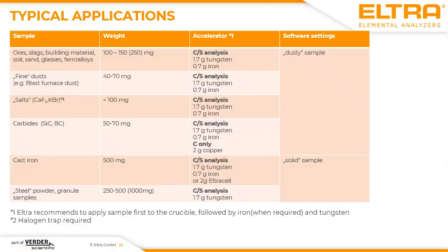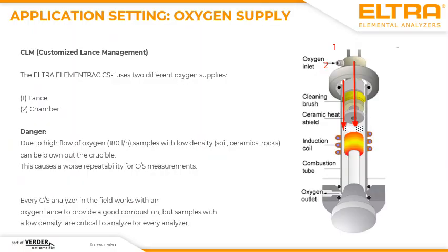On the right side of this table, you'll find the information software settings, dusty and solid sample. This is especially created for the settings of the Elementrac CS-i because this analyzer can provide you different combustion steps to make sure that your sample is on the one hand combusted completely, but on the other hand, the sample is not blown out of the crucible. The effect of the oxygen supply for a correct analysis is illustrated here. The Elementrac CS-i offers the chance to supply the oxygen in two ways. On the one hand, you have the lance.